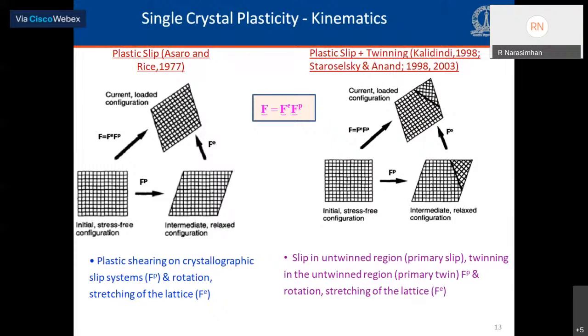So the kinematics involved is illustrated in this slide. The classical crystal plasticity formulation is due to Asaro and Rice, which is shown on the left side, and this was modified for treating twinning as a quasi-slip process by Kalidindi and Staroselsky and Anand, and that is shown on the right side here. Both these formulations involve a multiplicative decomposition of the deformation gradient into an elastic part Fe and a plastic part Fp.